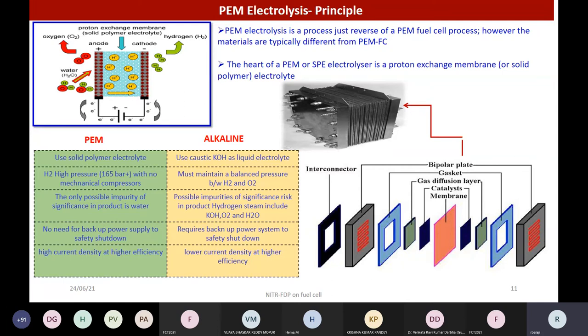Though if you are using titanium for flow field plate and current collectors, it has a tendency to get oxidized during the electrolysis process. That may increase the overall cell potential and may lead to further voltage loss. So in order to avoid such a phenomenon, we need to platinize the titanium mesh as well as the titanium flow field plates. So these are the reasons that make the system not cost effective. But we need to do it, otherwise the durability of the system will be a question mark.